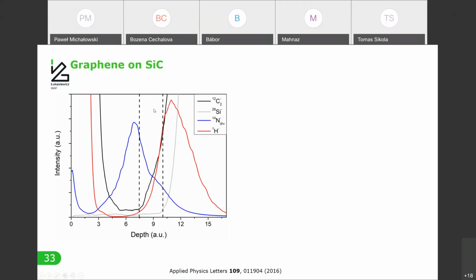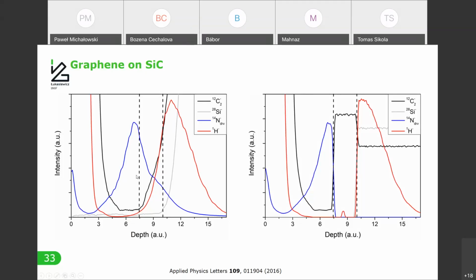So the graphene is between the dashed lines, and we can see some organic contamination staying in this chromium capping layer and maybe diffusing, maybe penetrating the graphene. It was not really very clear. But then exactly 5 years later, I repeated the same measurement, but with much higher knowledge, and after accomplishing all the data that you've seen before. So I knew that I can make the analysis better, because I got better with this tool. I understood how to work with it. So I repeated the measurements on exactly the very same sample, and the result is shown here.